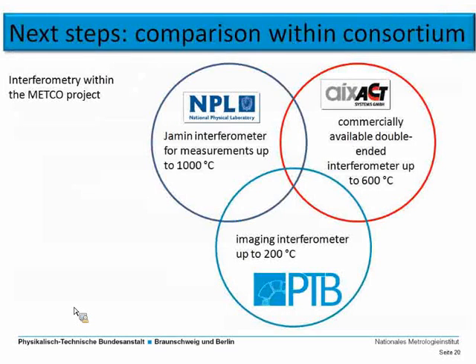And within the METCO project, we're not the only ones doing interferometry. We just introduced our imaging interferometer with our temperature range up to 200 degrees centigrade, but other groups like NPL are doing interferometry as well. They are equipping their Jamin interferometer with a furnace so that they can measure their samples at really high temperatures, up to 1000 degrees centigrade.